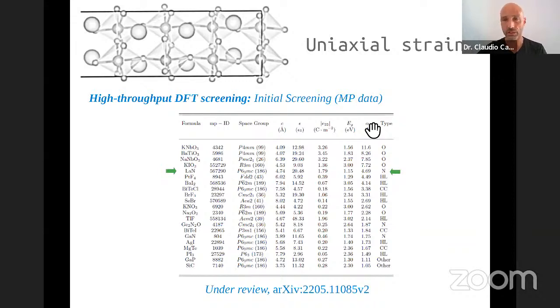However, that's not typically the case, because materials that have a large piezoelectric coefficient also have, of course, a large dielectric constant, right? So maybe that's why there are many materials that have just been overlooked for this potential piezo-photocatalytic application, right? So, for instance, we found one material that hasn't been considered so far for these applications, or in this context, which is lanthanum nitride, right? It presents quite a large alpha eta value, right?